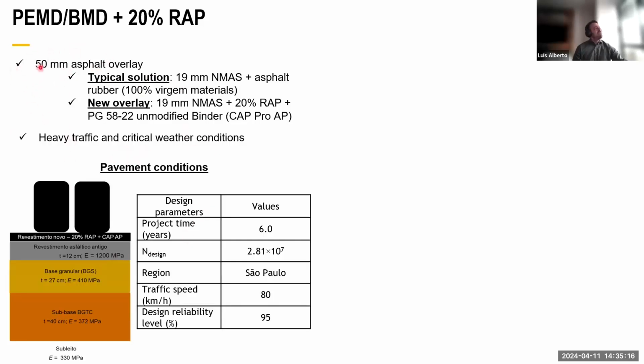This is a 50mm asphalt overlay, and the typical solution on this highway is a 19mm nominal maximum aggregate size with asphalt rubber. So on this highway, people usually do a 50mm layer with asphalt rubber and 100% virgin material. So our challenge here is using a performance engineered mix design to replace this layer by using about the same gradation, but with 20% of reclaimed asphalt pavement and a 58-22 unmodified binder. It's a kind of binder designed for rejuvenating the RAP. So the question is, will this new mixture be able to support this traffic?